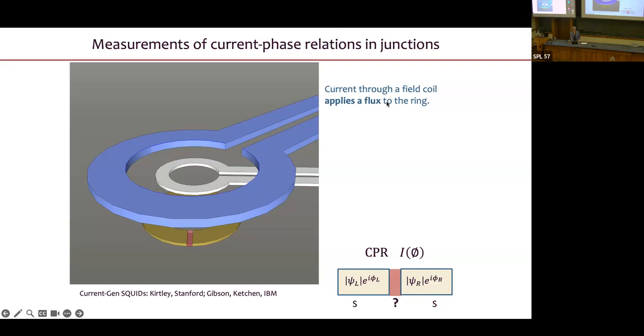So what we do is we put a current through the field coil that applies a flux to the ring. That's the ring that we're measuring down there, the gold ring. And that causes a current to flow in the ring. How much current flows in the ring depends on the current phase relation of the weak link.